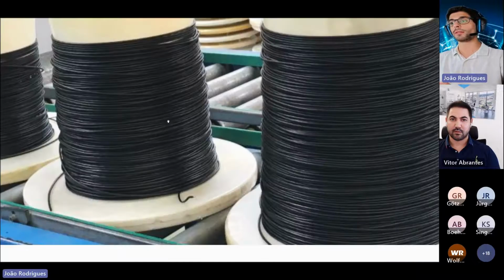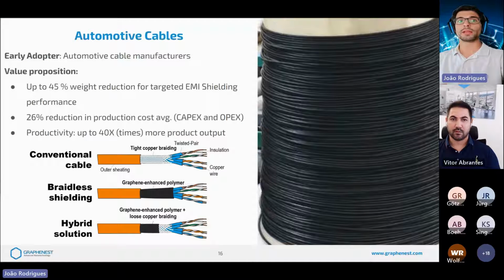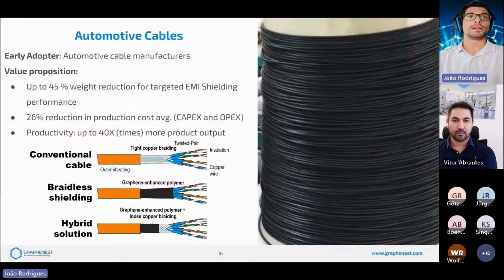But going a little bit more into detail, we developed a cable prototype that uses a graphene-based polymer as the shielding layer. Because conventional Ethernet and data cables that are also employed by the automotive industry use a tight copper braiding mesh and aluminum foil for shielding purposes, as you can see here on the figure.